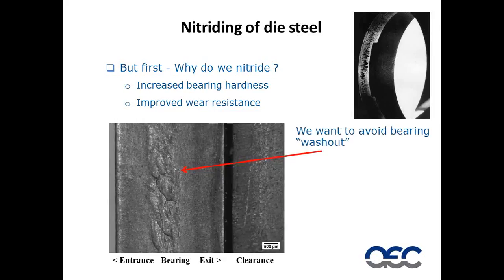If we look at that washout under a microscope, here's the bearing length running from here through to here. The red arrow is pointing at this premature wear of the bearing. This gives you a poor surface finish on your extrusion, and as such leads to a reduction in the die life. Of course, any reduction in die life increases your cents per pound for your extrusion for your die cost. So this is a significant cost in our extrusion that we need to keep under control.